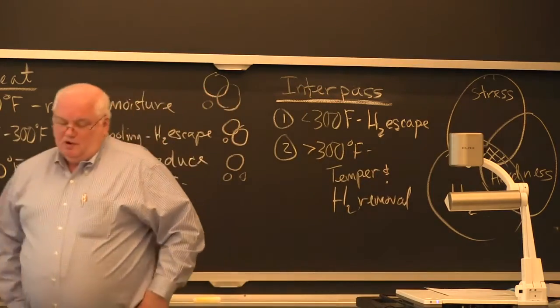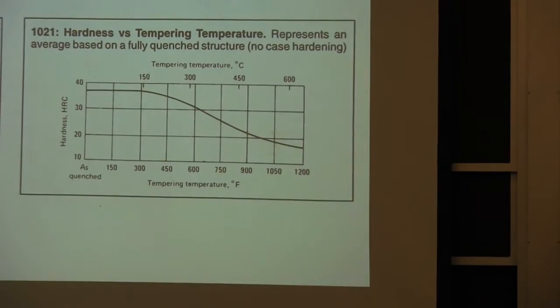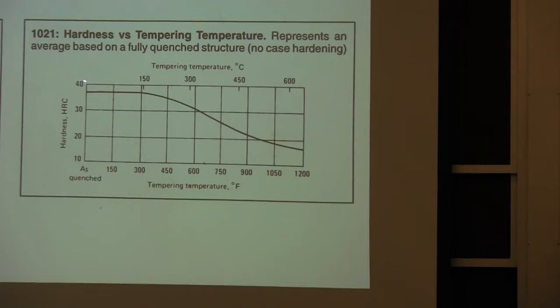And in fact, this is a tempering curve I showed you before, that basically, if you take a piece of steel and you quench it to its maximal hardness for a 1021 steel, the maximal hardness, which is a function of carbon content, may be Rockwell C 37 or 38. You get above 150 C, 300 degrees F, and the thing will start to soften by tempering. And you temper between 300 degrees and 600 degrees Fahrenheit. You avoid 600 to 1,000 because you get something called temper brittleness in steels, which, this is not a metallurgy of steels, this is supposed to be a welding course.